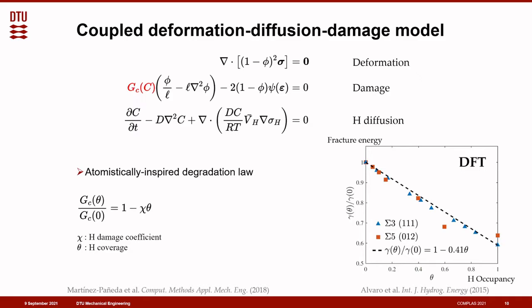The logic that we follow is an atomistically inspired degradation law. So based on atomistic simulations, what we see is that the fracture surface energy decreases with the hydrogen occupancy. So quantitatively, by running atomistic or DFT calculations, we can see how much the fracture energy decreases with the hydrogen content. So for example, if your interface is full of hydrogen, which corresponds to an occupancy of 1, you reduce your fracture energy by 40%. And that explains why hydrogen is so dangerous for metallic materials.